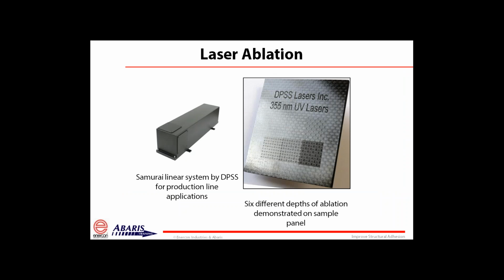You can barely see the ablation level here, where it has changed the matrix without getting to the fiber level. You might say the same thing about the second area here. It's about a 1 inch square. As you get into the third, fourth, fifth, and sixth level, they're actually getting down into the fiber itself. Once you're getting down to the fiber, you have changed the surface completely that you're trying to attach to. Remember that we want to attach to the matrix on the surface or a surface matrix resin that has a modulus that's compatible and a surface energy capability that's compatible with the adhesive that we want to apply.